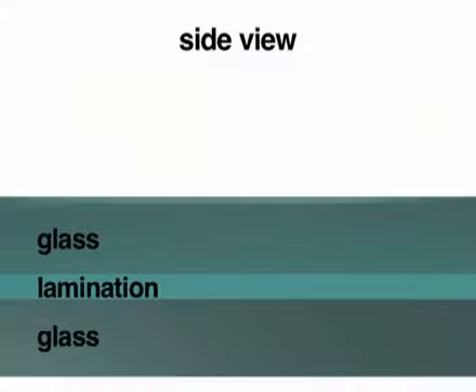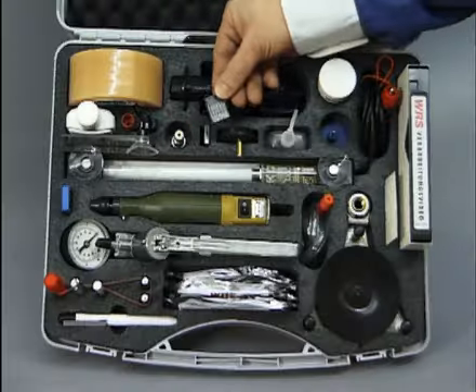If there are star breaks, 2 or 3 fine line cracks starting from the impact point, it frequently happens that one or the other fine crack has no direct access to the impact point, so that the filling resin is unable to flow in. In this case, drilling is required to establish a connection.